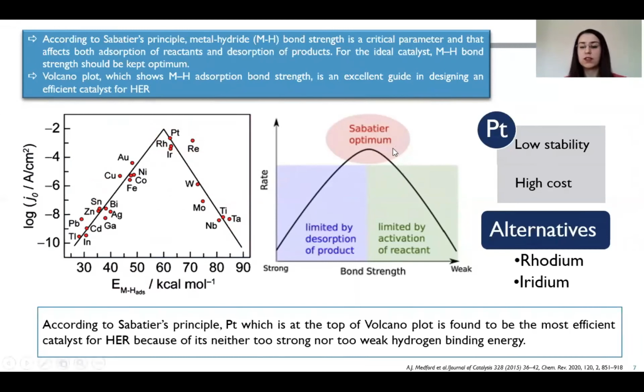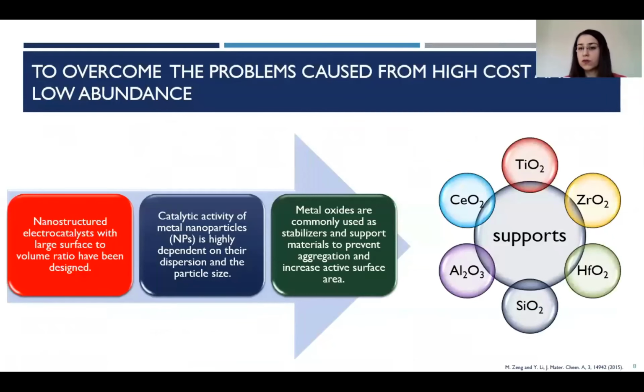to be the most efficient catalyst for the hydrogen evolution reaction because it has neither too strong nor too weak hydrogen bonding energy. However, platinum suffers from low stability and high cost. So, rhodium and iridium metals can be an alternative to platinum. However, these metals also suffer from high cost and low abundance.